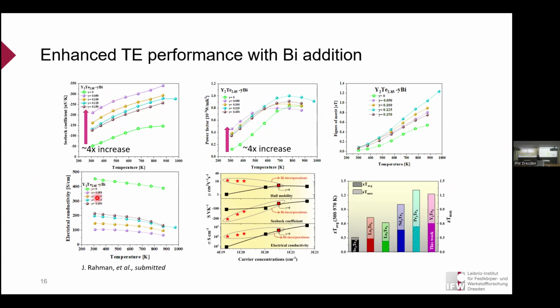But of course, it corresponds to a decrease of the conductivity, also by a factor of around 4. But since for the Seebeck coefficient, we have a square here, at the end of the day, we still get a power factor improvement, also by a factor of 4 at around room temperature.